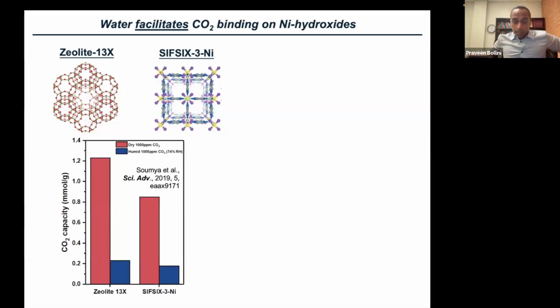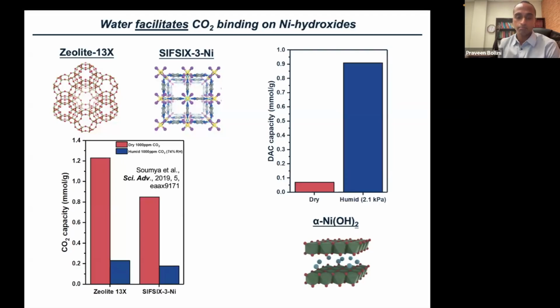So what you'll see in the data on the left specifically are two classes of materials. One's a zeolite, specifically zeolite 13X, and a MOF, which is SIFSIX-3-Ni, which uses open metal sites to adsorb CO2. And you'll see in the data here that both the zeolite and the MOF, as is typical for most carbon capture sorbents, when you expose them to humidity, they actually adsorb less CO2 than when you capture CO2 under dry conditions because of competitive binding with water. The sorbent system that I'm trying to describe here is fundamentally different in that water, in fact, aids in binding CO2 rather than inhibits the binding of CO2.